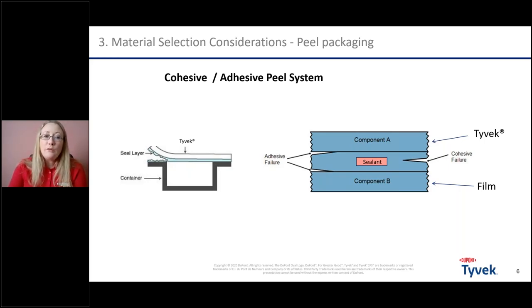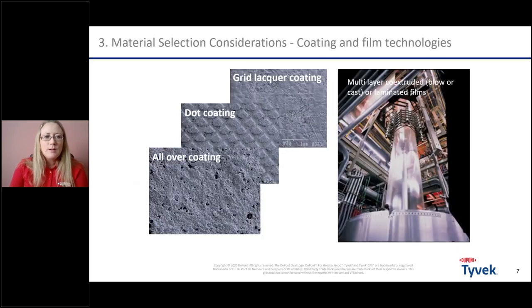So there are different systems. There are even more, but two very common ones are cohesive and adhesive peel systems. When you look at the blue picture here, you have component A, which could be Tyvek, and component B, which could be the film, and you have the sealant in between, which could be linked to the Tyvek or linked to the film, right? Principally, an adhesive failure would be when the sealant comes off from the Tyvek or the film when peeling off, while a cohesive failure is when the sealant fails within itself. For a good peel packaging with a stable process window, I would recommend a cohesive peel system, with Tyvek packaging at least. Here, as said, the sealant can be either on the Tyvek or paper side or on the film side.